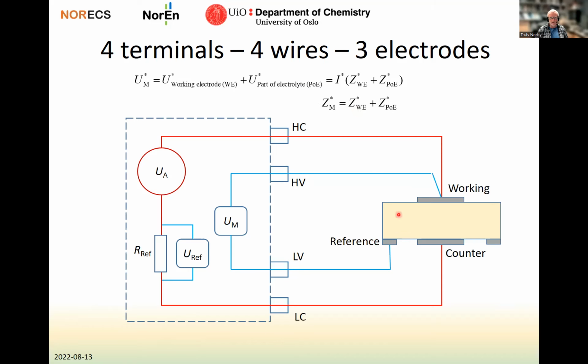Now we can split one of the electrodes into 2 electrodes, a reference electrode and a counter electrode. The reference is contacted by the voltage probe, while the counter electrode is supplying the current. Now the current is running through the sample like this, and we pick up the voltage between the working electrode and the reference electrode.